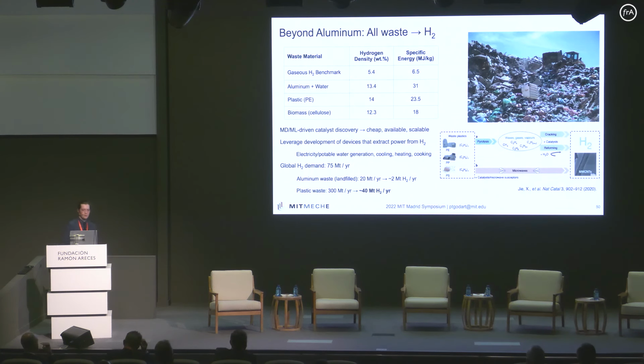And I'd like to leave you with this other observation that aluminum is not the only hydrogen-dense material in our landfills. Aluminum, again, is about 10 to 13 weight percent. But plastic, and polyethylene in particular, has a hydrogen density of 14 weight percent, and biomass has a hydrogen density of 12 weight percent. And there's some very interesting research going on using some machine learning techniques to develop catalysts for doing this effective pyrolysis-type process where you're separating out the hydrogen from these different materials and leaving behind solid carbon.